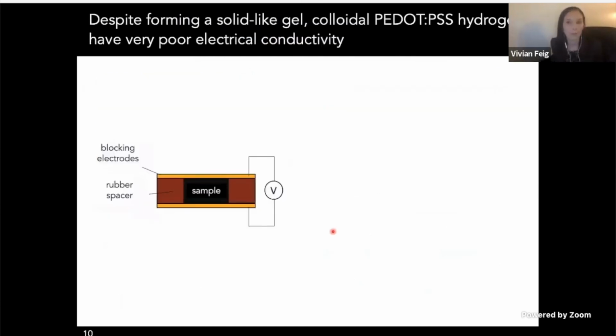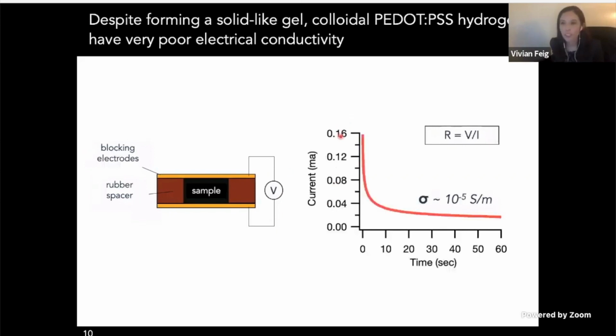The way we measure conductivity is by sandwiching our gels between 2 gold electrodes. And then first we just apply a constant voltage across the gel and then look at what the current response is. But unfortunately, we see that we just get a transient current that quickly drops to near zero, indicating that there's really negligible electrical conductivity in this gel.